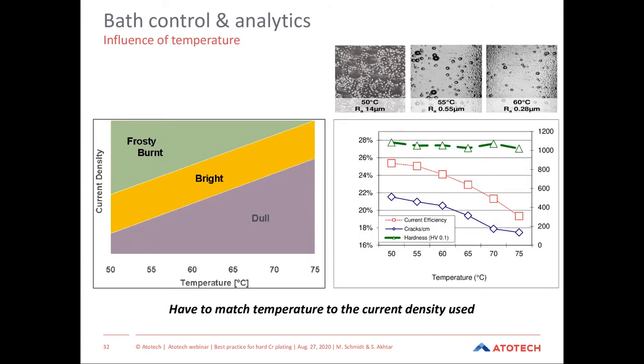Here you see the influence of temperature on the plating bath, where a drop of temperature will mainly cause roughness and nodulation. You can see this in the top pictures. When the temperature is dropping, the surface is getting very, very rough, and you get these little bubbles, which you can also feel with your nails on the part.